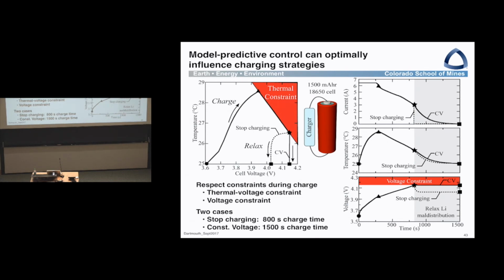And what we see is charging. As the battery charges, of course, the voltage goes up and the temperature goes up. But at this point, we run into a constraint that says if the temperature is what it is, you can't exceed a certain voltage. Right, so smart chargers need to respect these constraints because you can overcharge, you can make dendrites, you can have all kinds of problems. So then what happens is, to stay on this constraint, but we still want to keep charging, the controller rides down this constraint until it hits another constraint that says I don't want to charge above 4.15 volts, because that would also be a damage mechanism.